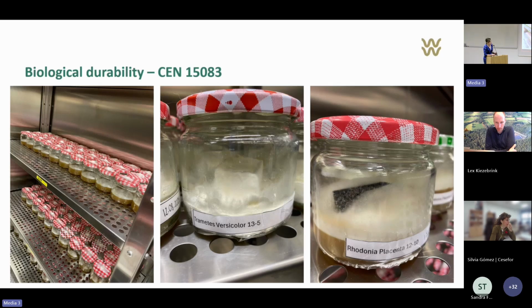Another test really relevant for our application is durability testing - big thanks to our crew who performed those tests. We tested against Trametes versicolor and Rhodonia placenta. During the first phase, we were already able to prove that the modified wood was achieving durability class 2, which was very good - that was one of our milestones.